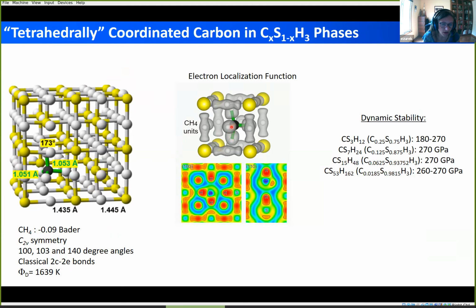Again, we see these strong carbon-hydrogen bonds, and we do not see any kind of bonding really in our electron localization function or using other descriptors such as the crystal orbital Hamilton populations between the hydrogen and the CS lattice. Dynamic stability here is found in a larger range of compounds in terms of the stoichiometry range, and also down to lower pressures, for example down to 180 gigapascals.